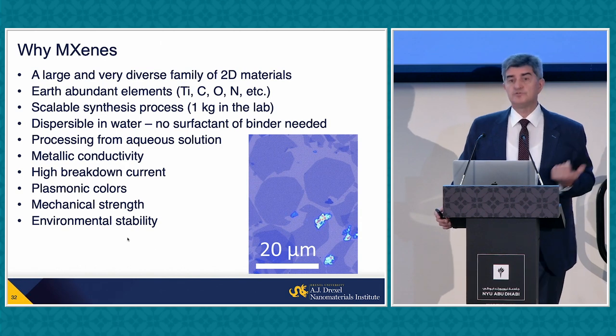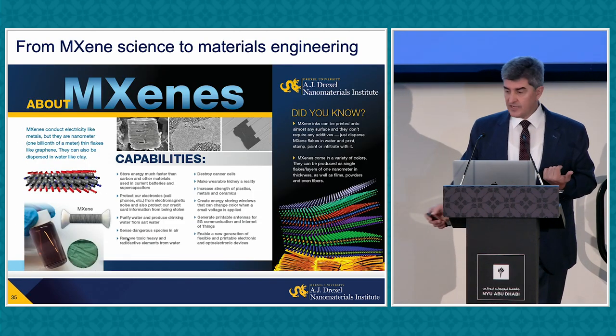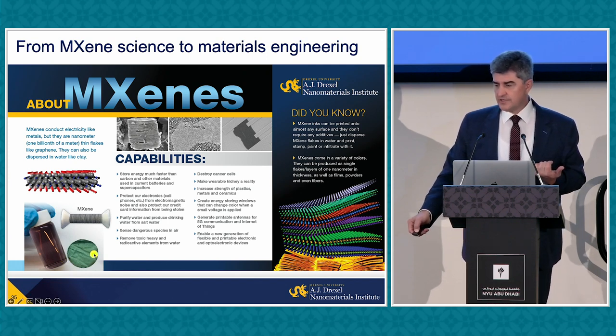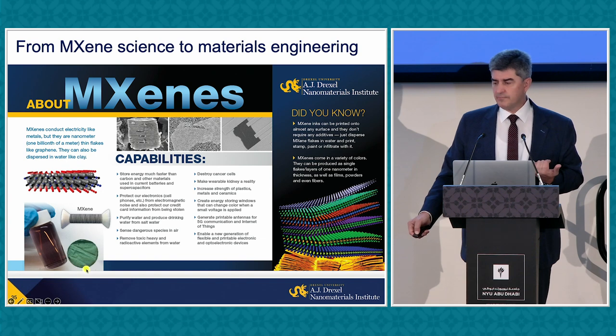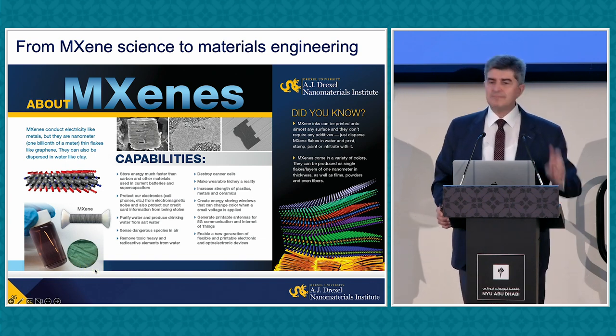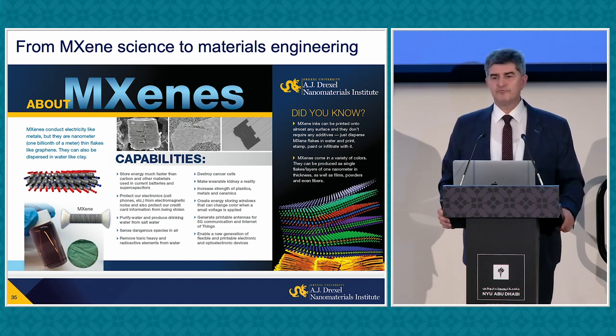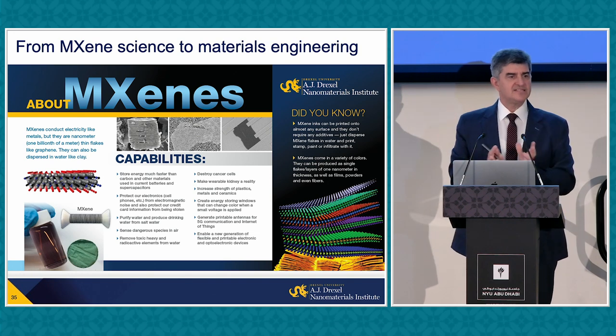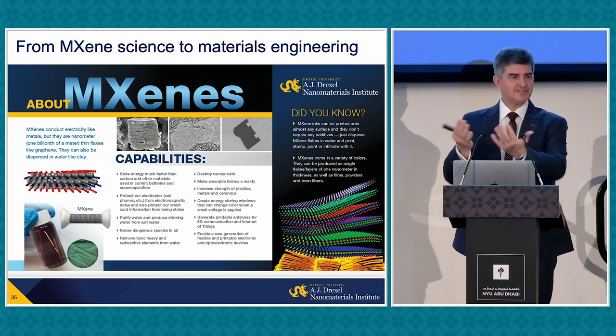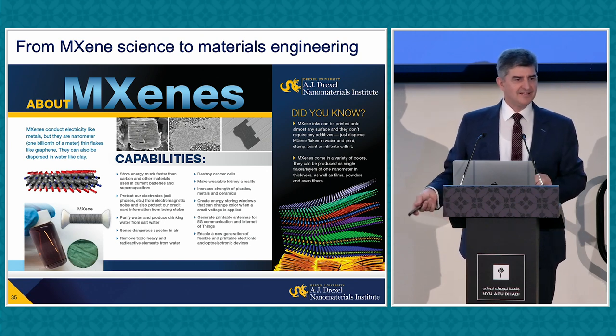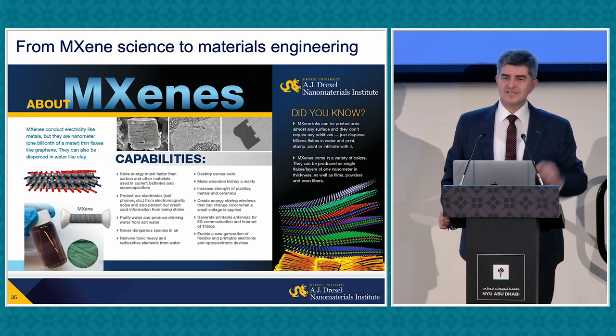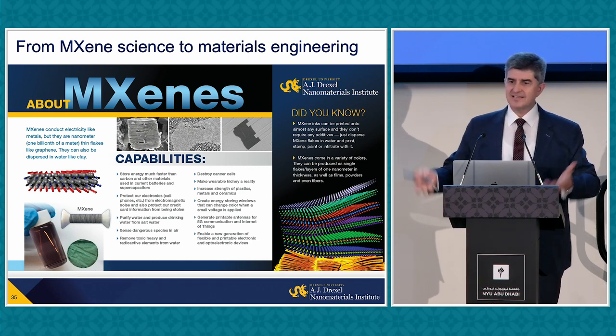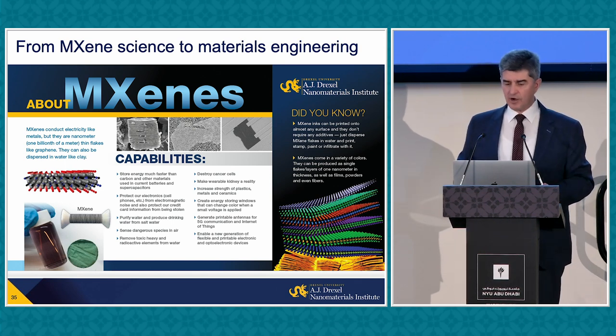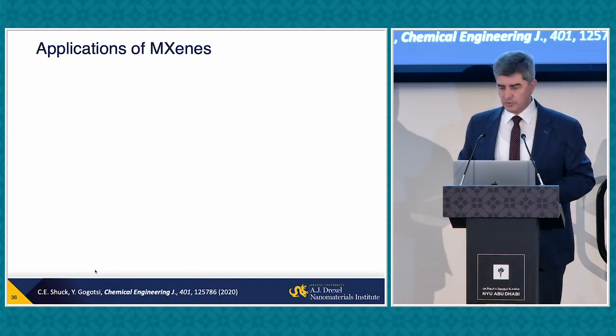They're stable, and you saw in my first picture, they have plasmonic colors. Actually, this is titanium carbide, Ti3C2. You may know that the first example of human-made nanotechnology, people claim, is the Lycurgus cup, a fourth century Roman glass cup, which is green if you look at its reflection, and red if you look in transmission. This is Ti3C2. It does exactly the same because it has a transverse surface plasmon at 550 nanometers, just like gold nanoparticles. There is a big difference. It doesn't contain gold. So we can make plasmonic materials, not out of noble metal particles, but of very common elements. And there are many other properties I'm not going to talk about today.